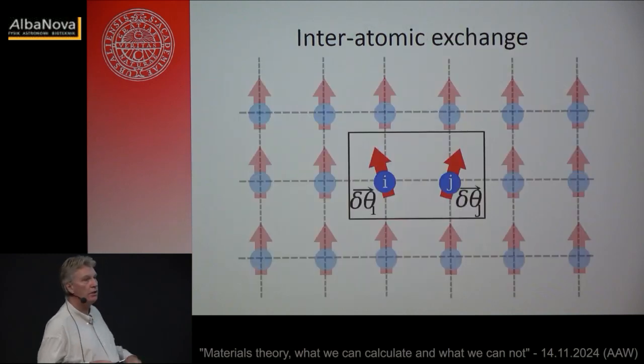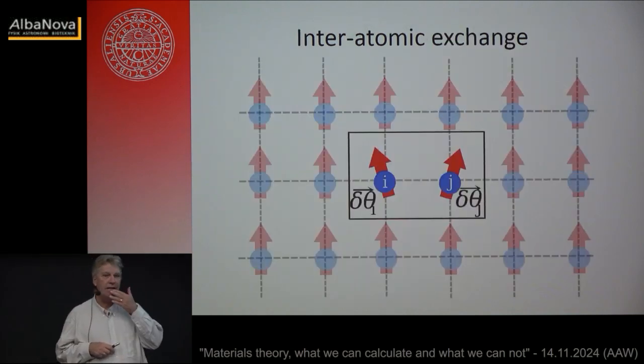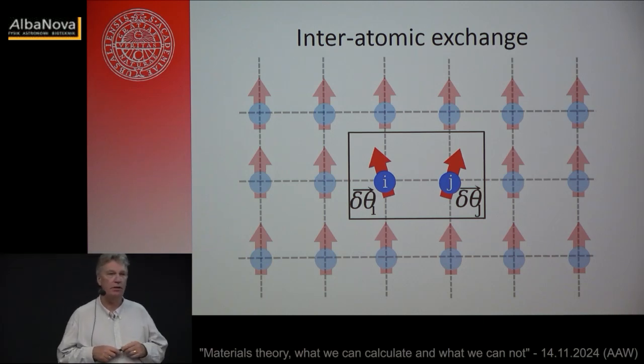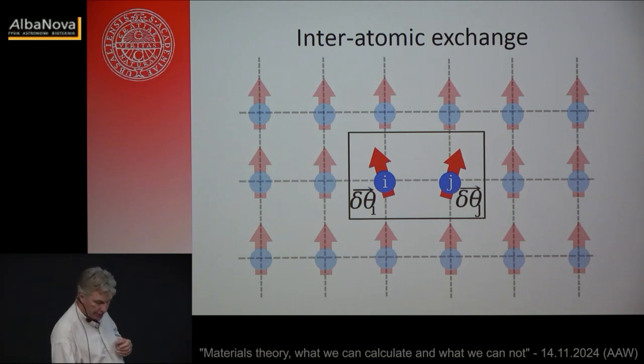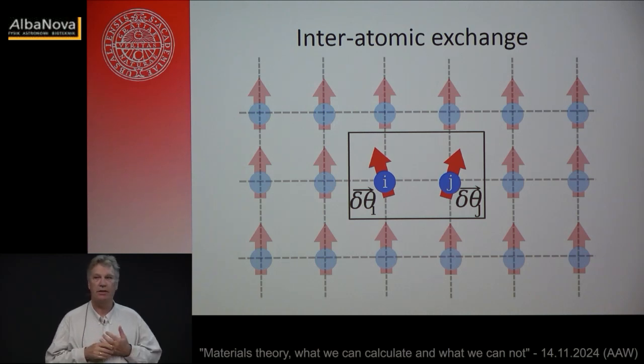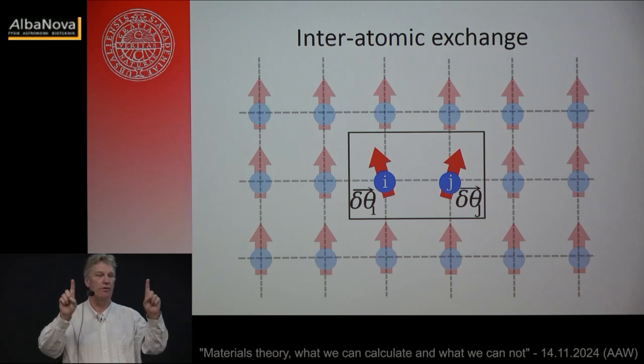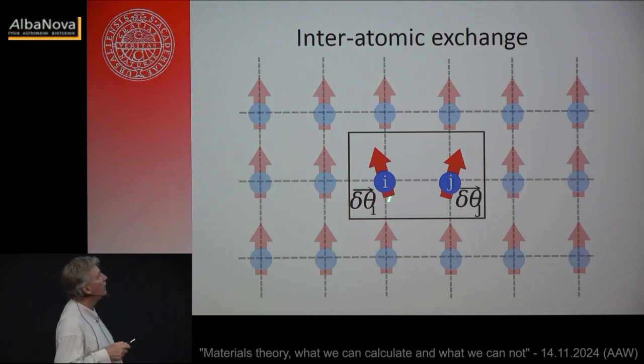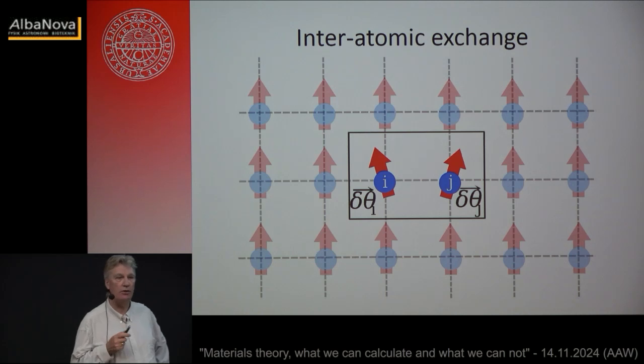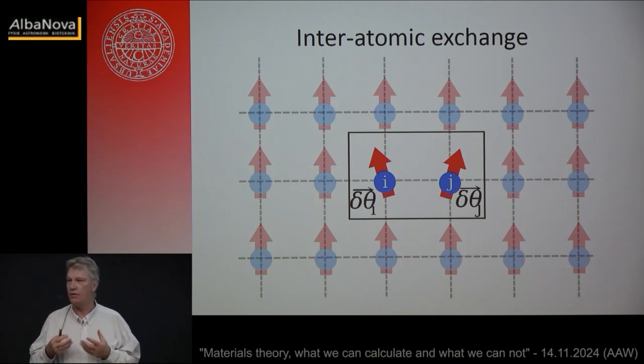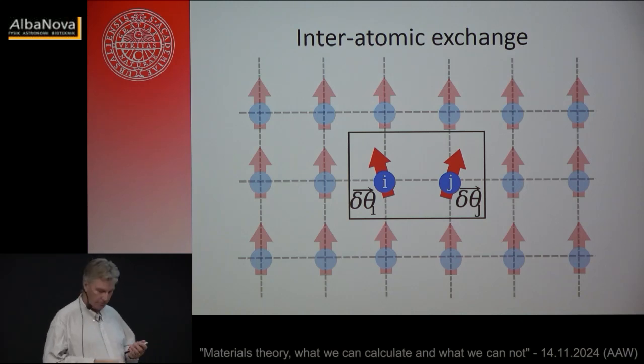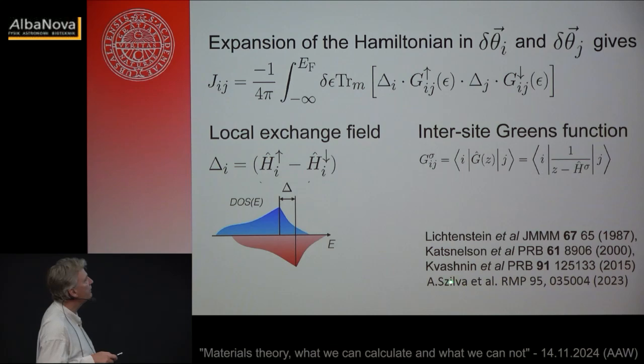That is something that also is a result of these kinds of calculations, and it's the result of work done by a very strong group in this field in Yekaterinburg in the 80s, and they said the following: if I have the Heisenberg Hamiltonian, and that's something that we all know, and I'll write it down in a second, how that describes magnetic interaction. And if I have two moments and I tilt them a little bit like this graph shows, I know how much energy that changes. Can I then calculate how much that energy change is also from my density functional? And if I can do that, I can find a way to map information from the density functional to a simpler Heisenberg Hamiltonian. This was done by Lichtenstein, Katsnelson, and then we jumped into this much later, Kvashnin, and we wrote a review article just last year.